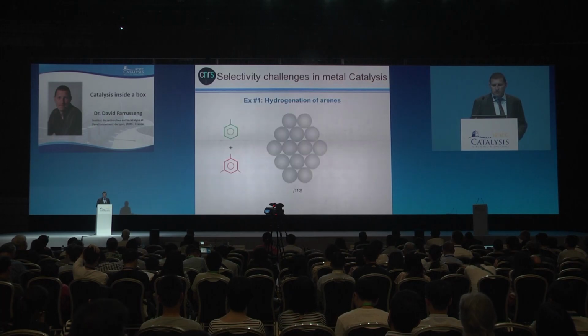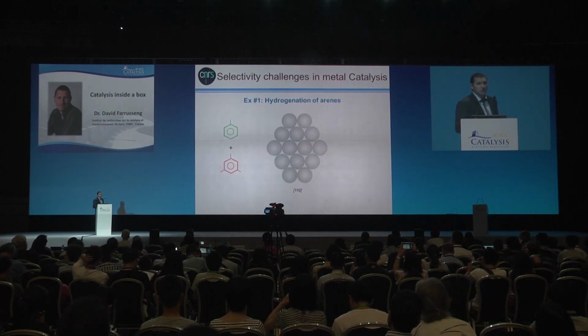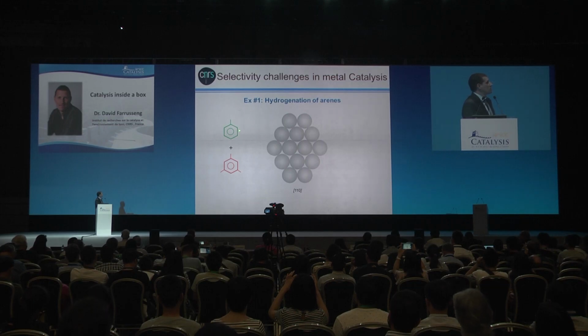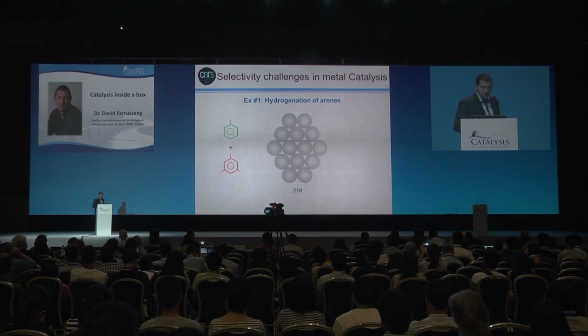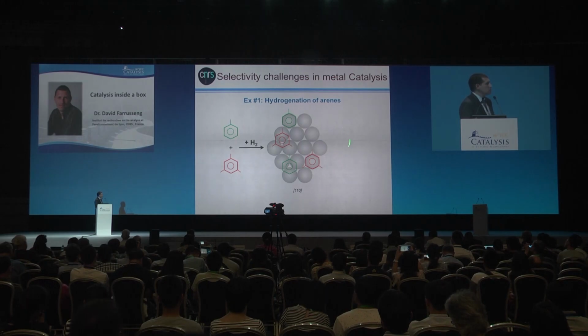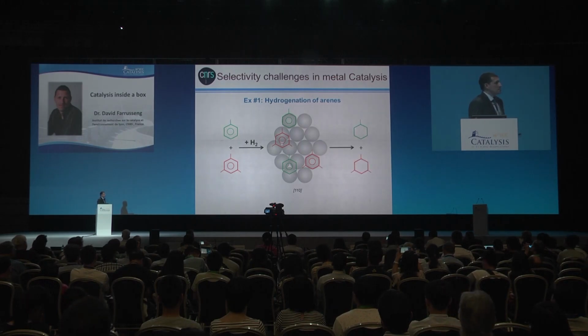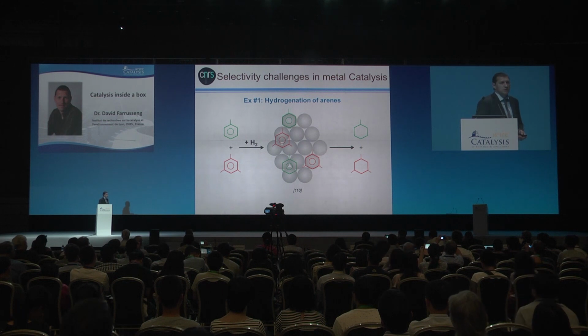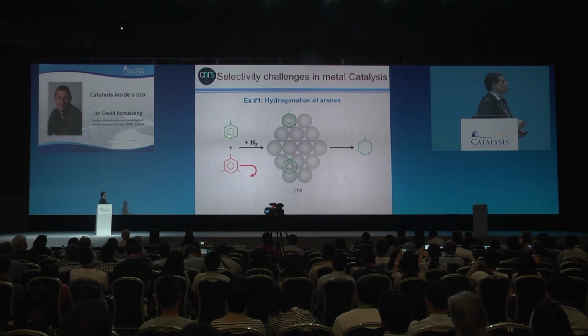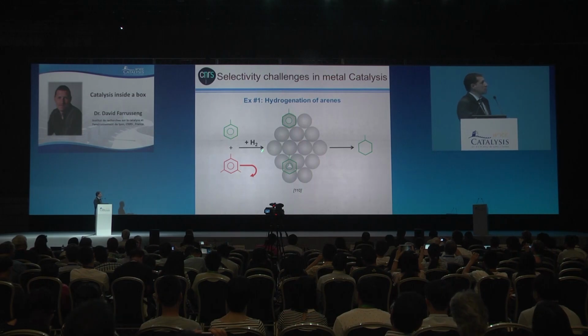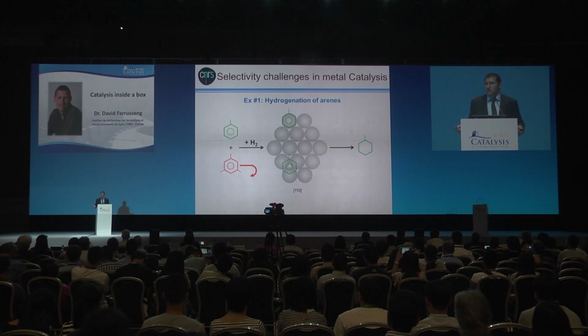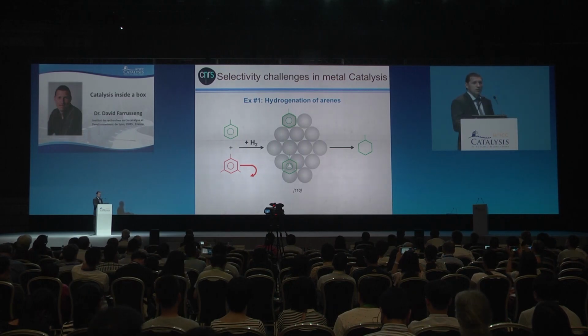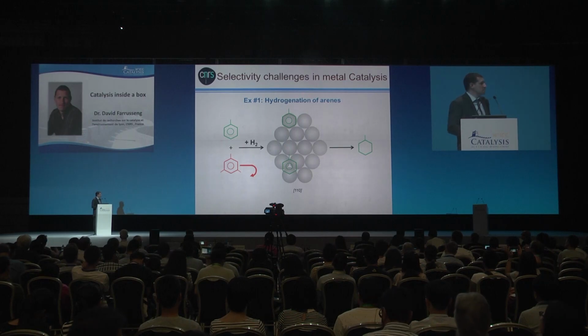And why is this important? Well, if you want to hydrogenate selectively toluene here and not trimethylbenzene, but they are both present in the medium, well, they will both get adsorbed at the surface of a metal particle, this is the surface, and eventually react to lead to the corresponding alkanes. If you want to selectively convert the toluene, then you shall prevent the trimethylbenzene from adsorbing, otherwise you have lost. And I will show you how we can use the zeolite membranes to make this sealing.